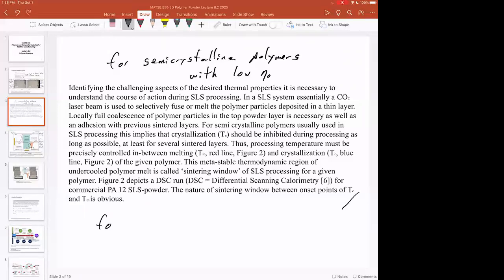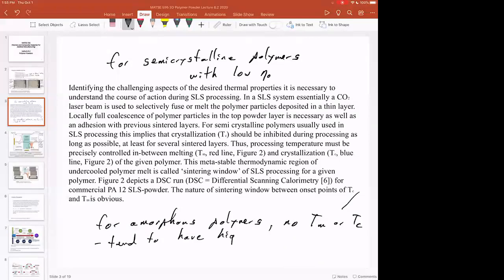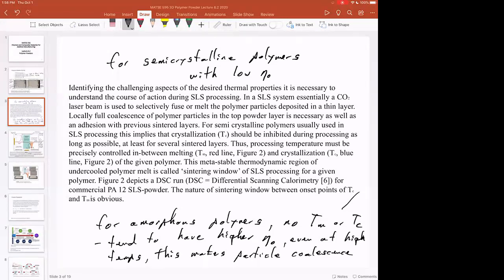So for amorphous polymers, there's no TM or TC, and they tend to have higher zero shear viscosities, even at high temps. Which makes particle coalescence difficult, which means you have poor sintering behavior of amorphous powder. So having a high zero shear viscosity makes particle coalescence difficult.